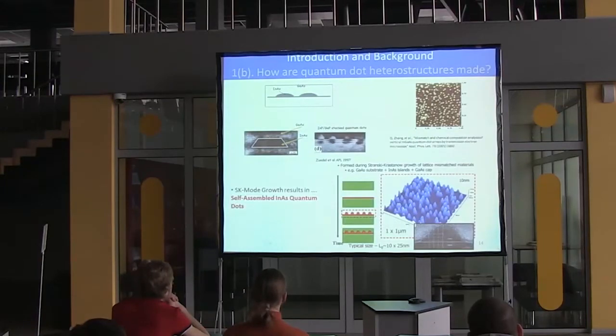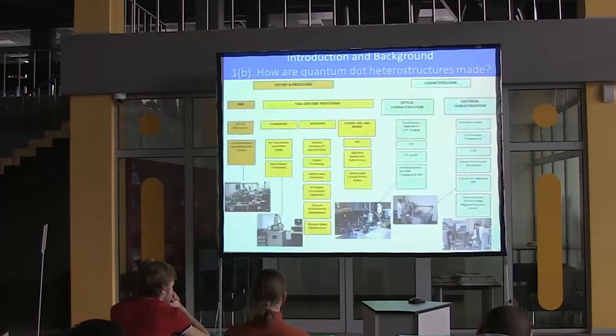Here are some pictures, which will make you happy again. We've got the example of the islanded growth. You see a wetting layer, which is the thin gray stuff, and you see the indium arsenide islands on top, and here's a picture of how they may look. STM pictures. This is a TEM picture of one of ours, of how these growths look, and they can be surrounded completely by the gallium arsenide. So there's your three-dimensional nanostructure we were speaking about. In my group, we can do that. We have MBE. We have lithography, so we can put contacts on this thing and make a laser. We can also check how it behaves. And I showed you that last time.